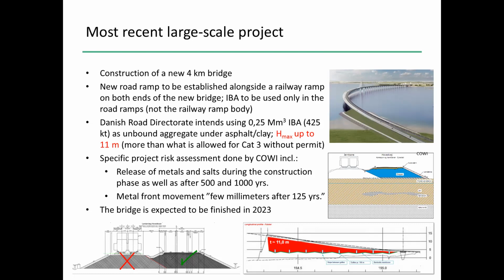So that's why a specific risk assessment was done by a consulting company, COWI, who calculated the release of metals and salts during construction as well as the use phase, and after 500 and 1,000 years. The major result is that the metal front movement is roughly a few millimeters after 125 years. So the project got a green light and the bridge is expected to be finished in 2023.